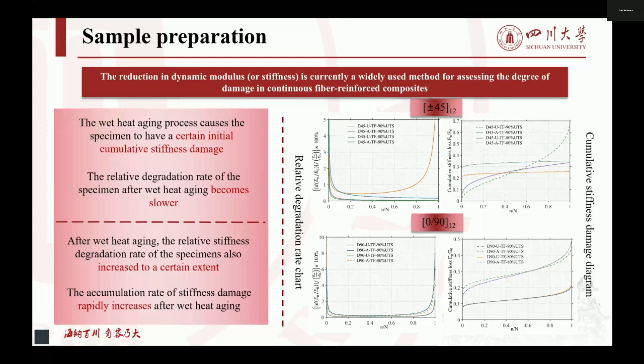After hygrothermal aging, the cumulative stiffness damage rate of the 45-degree test specimens decreases. It is also evidence that the relative degradation rate of the 45-degree test specimens after hygrothermal aging becomes slower. The hygrothermal aging test results in a rapid increase in the rate of stiffness damage accumulation in laminated plates with a 90-degree layup angle during fatigue testing.